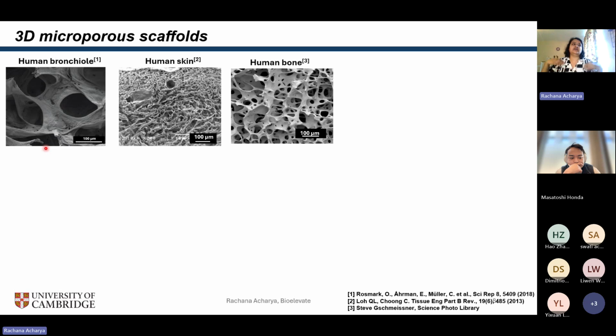So these are SEM images of different connective tissue in our human body. If you see, they have this very characteristic structure of a microporous environment. Of course, the length scales of these pores are different throughout different parts of the body, but in general, you can see that it consists of this microporous structure, and this is what we want to replicate. So we take our trusted polymer, PEDOT:PSS, and luckily PEDOT:PSS is water soluble, so it forms a colloidal dispersion in water.